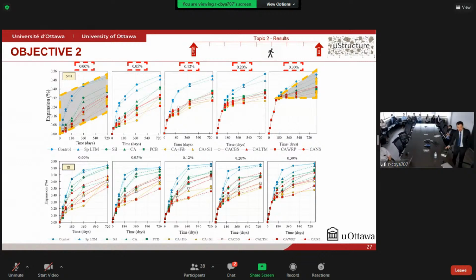So also I would like to highlight that the treatment in which we combine crystalline admixtures with waterproofing on average is the one that shows the best behavior for expansion, but also the combination of crystalline admixtures with fibers also shows one of the best behaviors on average.